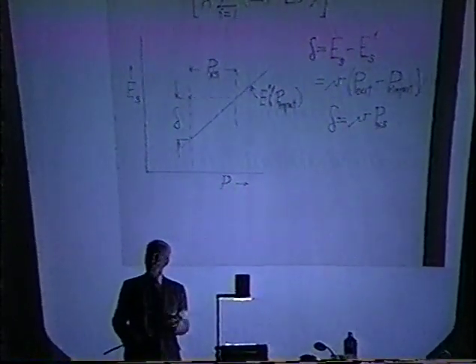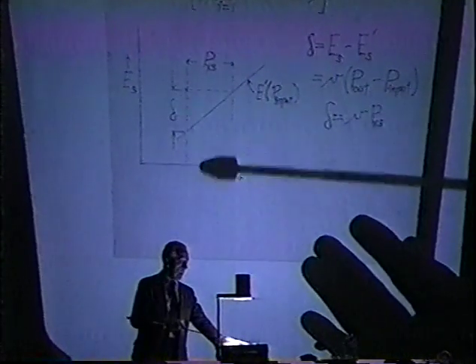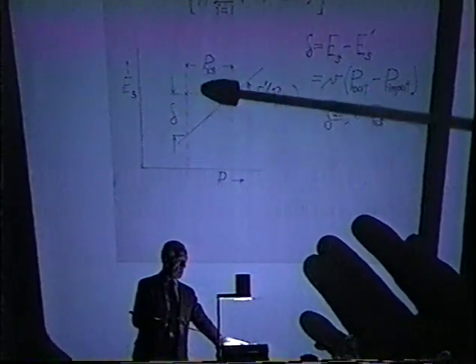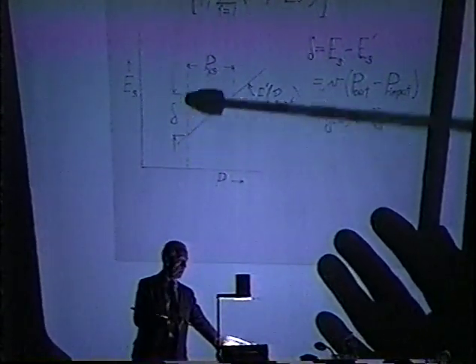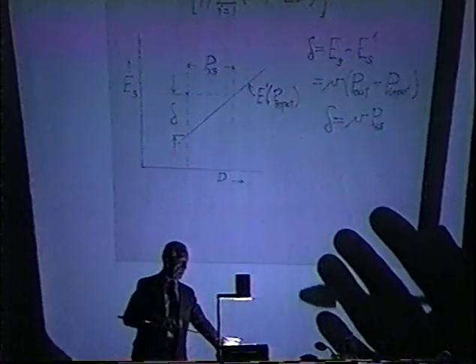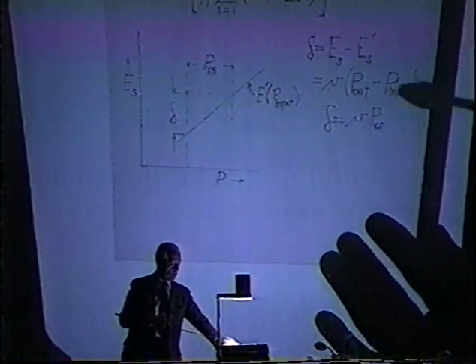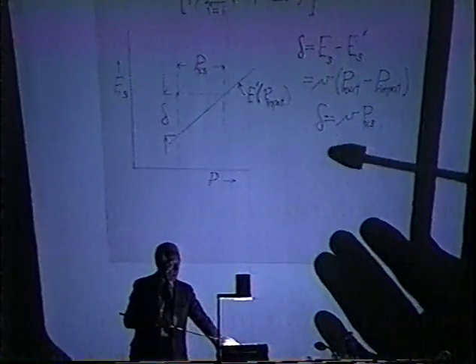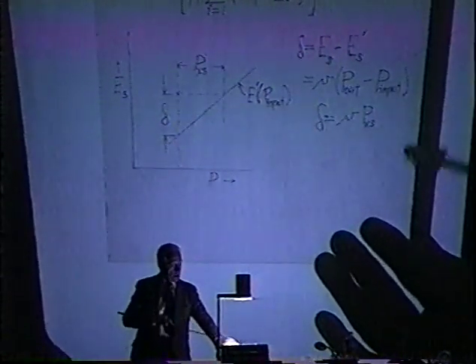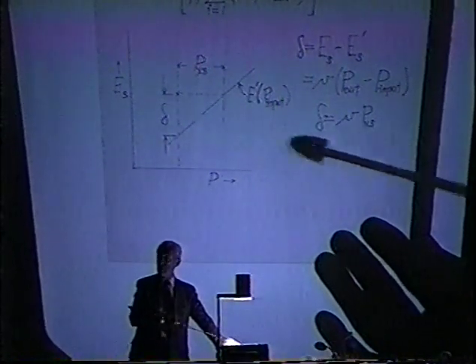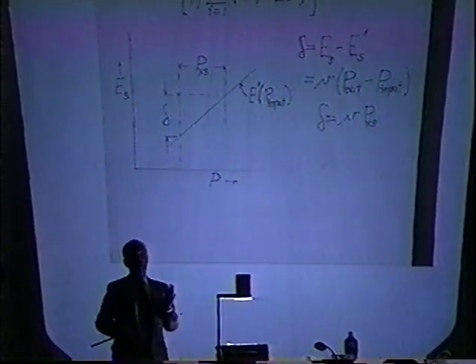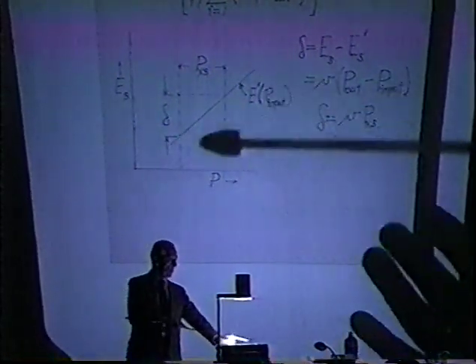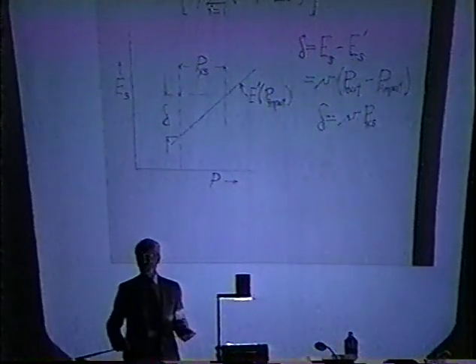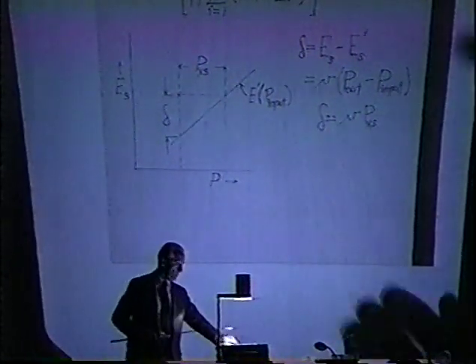In the power runs done with the deuterium gas, if I happen to obtain at this input power a single E sub S which lies here, north or above the calibration line, then I would say this is excess power. And I calculate how much that deviation, delta, represents in terms of excess power by a very simple equation, knowing the slope of this line. So the deviation, delta, is related to excess power simply by the slope of the calibration line. So what I have to establish is that this deviation is larger than statistical fluctuations or statistical random errors in my calorimetry.